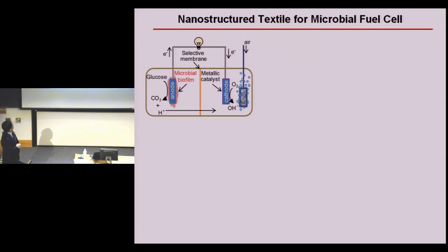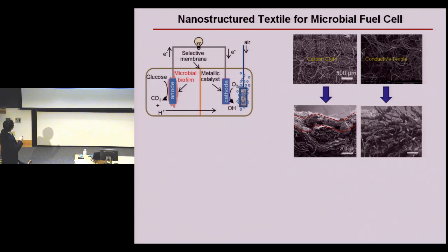So one last piece of example. I think this conductive paper or textile really opened a whole range of device applications. This is a very quick demonstration of using a conductive textile as an effective anode for microbial fuel cells. Basically, the idea here is we grow bacteria inside conductive paper or textile. This is the current technology: the bacteria can only grow on the surface of the conductor. In these conductive textiles, the bacteria can grow through the entire structure. So effectively, because of the size compatibility, we increase the amount of bacteria growing inside the textile.